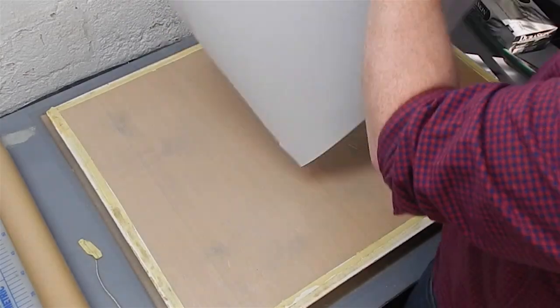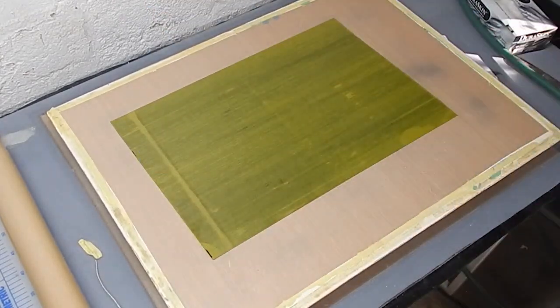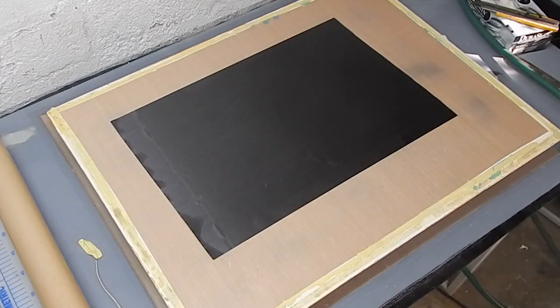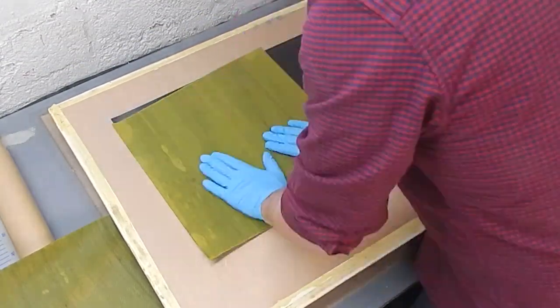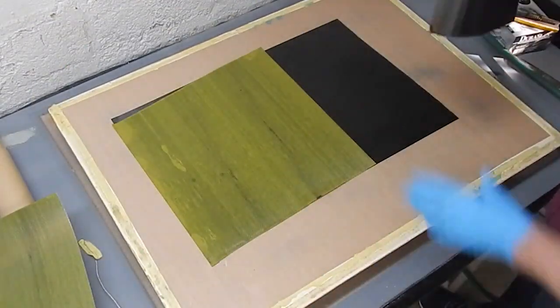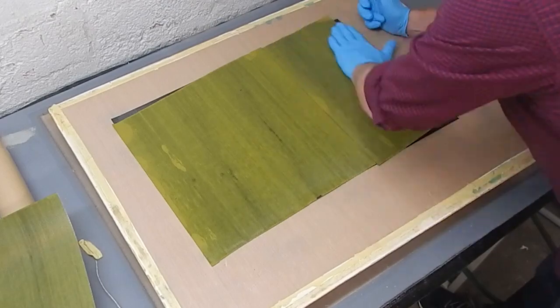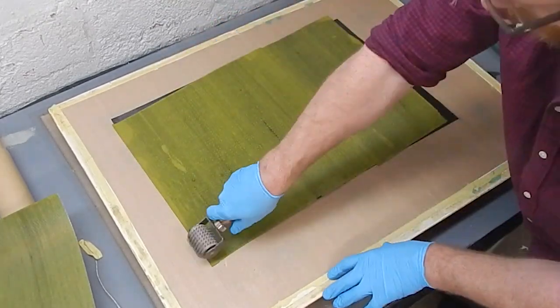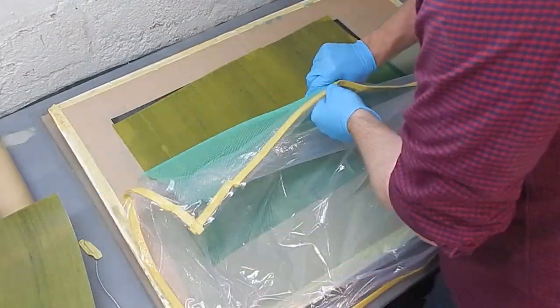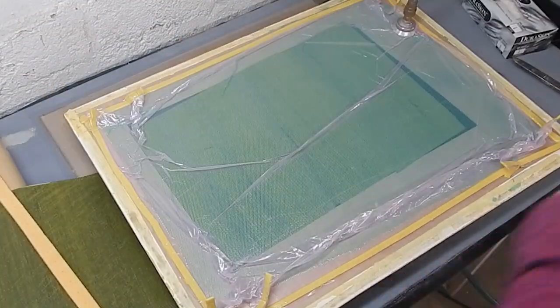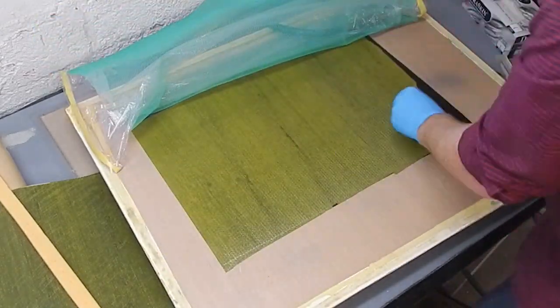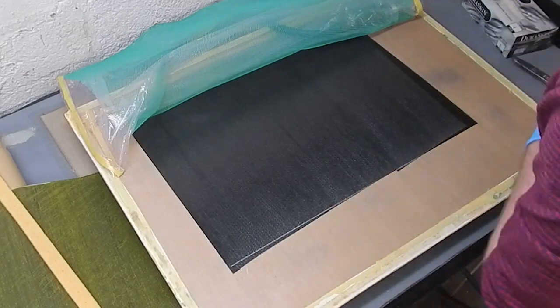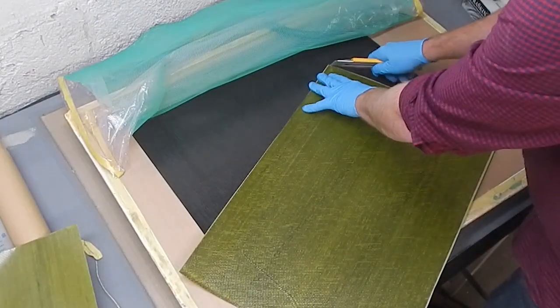So now I'll start laying up the actual panel. I've cut the carbon pretty sloppy here, but it's just three plies per skin, two zeros running the long way with a 90 the short way in the middle, and I'm just giving these a quick spike so I can leave the plastic on during the debulk. Ideally you take the plastic off just to get better exposure for the air to come out during the debulk, but it works pretty well doing it this way.